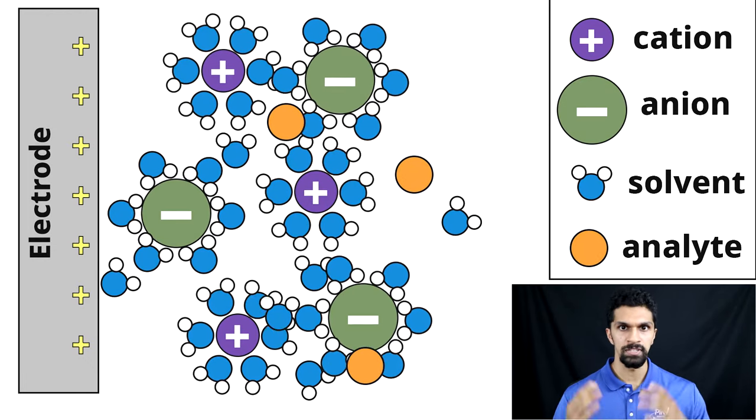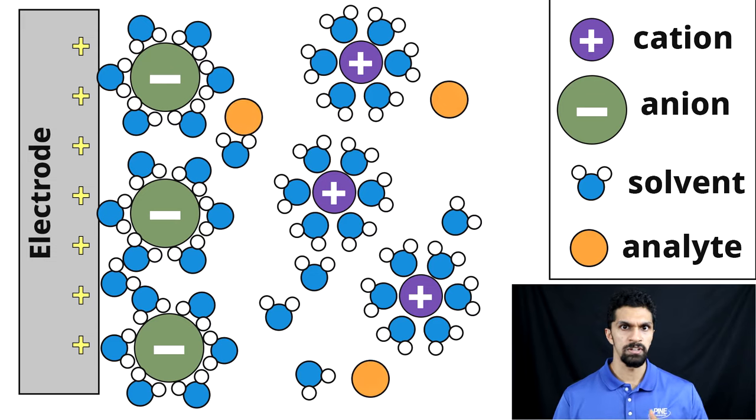In the symphony, we use our ears to discern at different frequencies what instruments were being played. With EIS, we similarly use frequency to deconvolute different electrochemical phenomena that occur on different timescales at different characteristic frequencies. One of the most powerful things about EIS is that we are able to probe different electrochemical phenomena because they occur at a characteristic frequency. Electrochemical processes can happen at the same time but occur on different timescales — for example, the charging of the electrochemical double layer happens on the microseconds timescale, but diffusion occurs on the hundreds of milliseconds timescale. Both processes are occurring on two different timescales but will occur simultaneously during an electrochemical experiment.